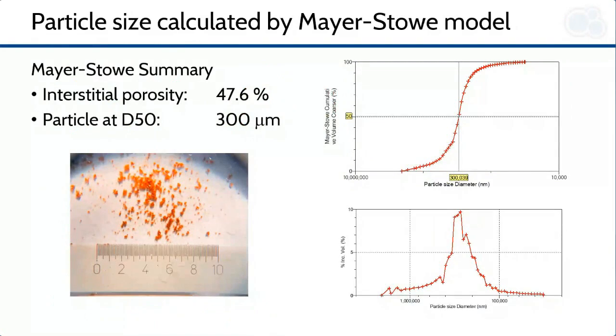Mercury intrusion provides for free also a measure of the particle size distribution. Intrusion at low pressure measures the cavity size and volume between the particles. This value is then converted to the particle size by using the Mayer-Stowe model. In this case, we have that particles at D50, 50% of the volume, are about 0.3 mm. This result is consistent with other sizing methods that have been applied to this coffee sample.